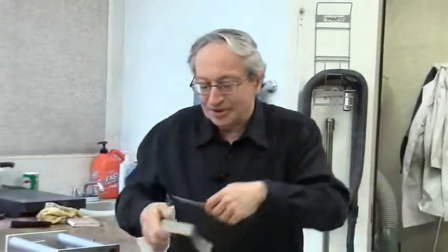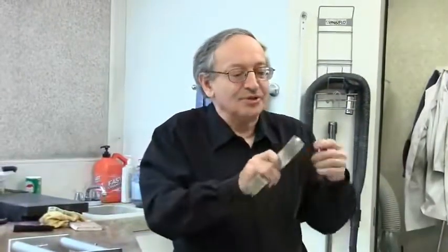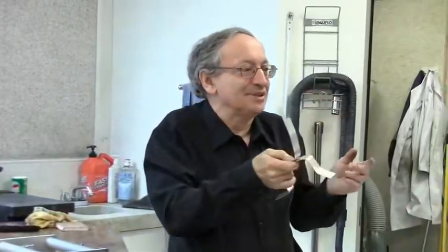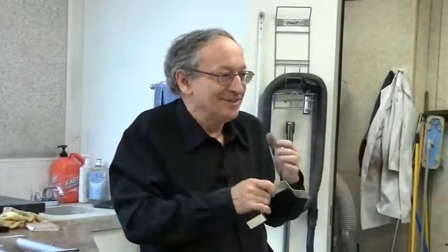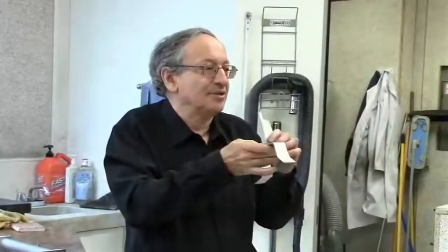Peel mode puts all the load on one line, because just the line where it starts lifting off, anything behind it doesn't see the load. So since all the load is concentrated on one line, which means geometrically zero area, it has to fail. Okay, and that's why you should be very, very careful. The same thing is true for soldering. If this was soldered, not done with epoxy, I could still rip it apart by hand.